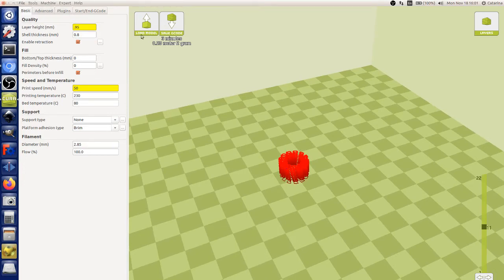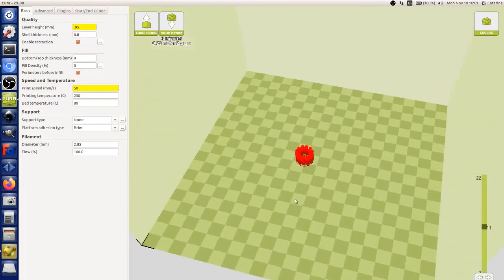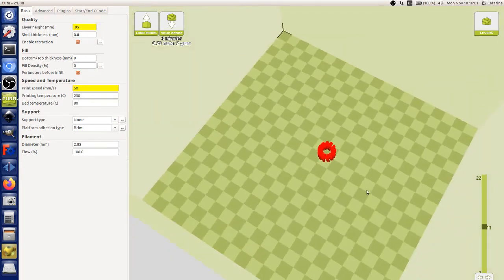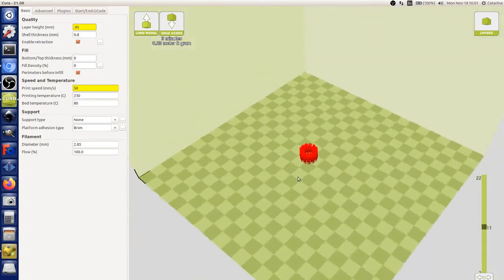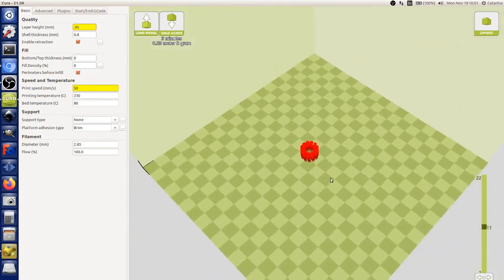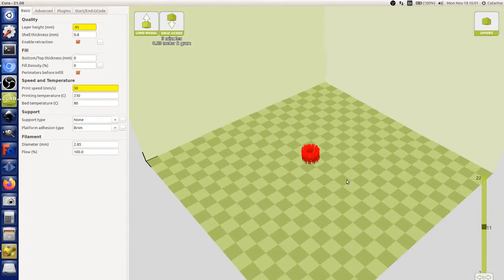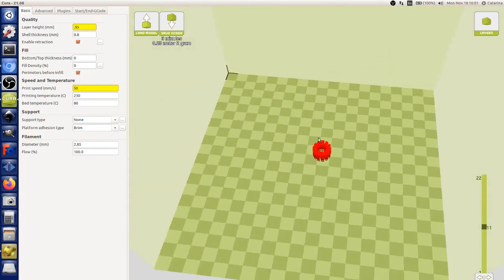Let's talk about the bed surface. So in our printer right now, our bed goes to 187 C stable working temperature, which is higher than just about anything out there. And it's a fast heated insulated bed. Now we notice that you have to get the bed temperatures right. So you can get the bed hot for some materials if you're using polyetherimide, PEI, print surface, which is a good surface, where when you heat it up, PLA sticks well to it. When you cool it off, it pops pretty much readily off.